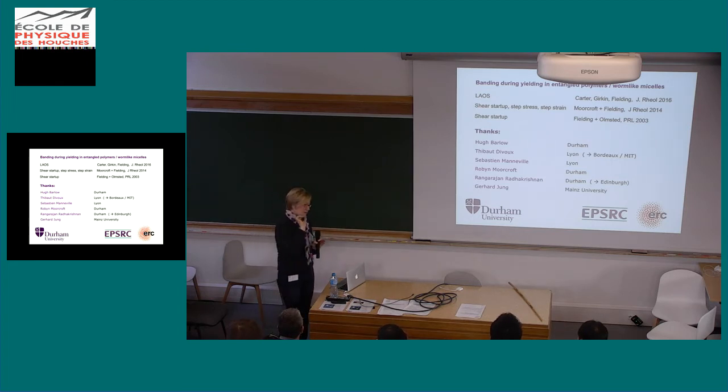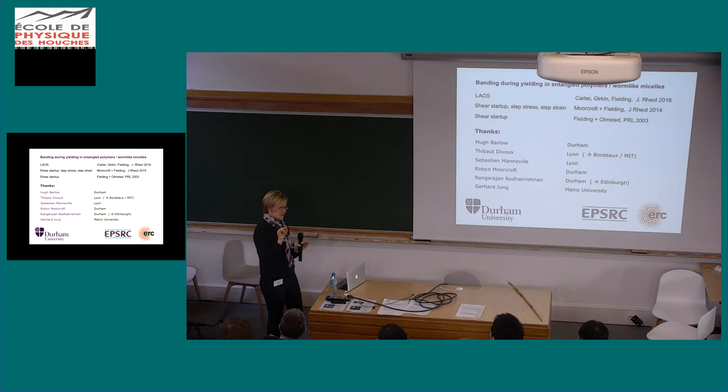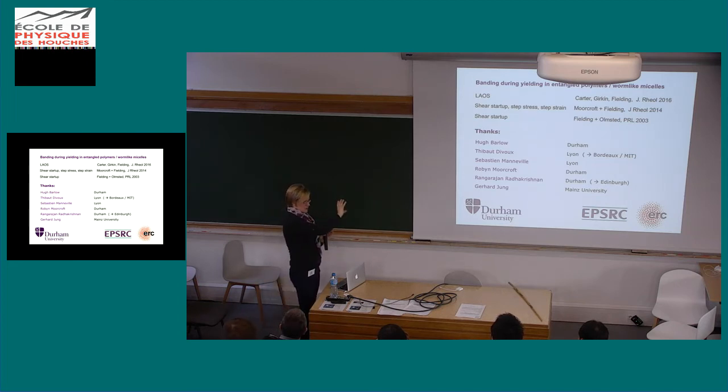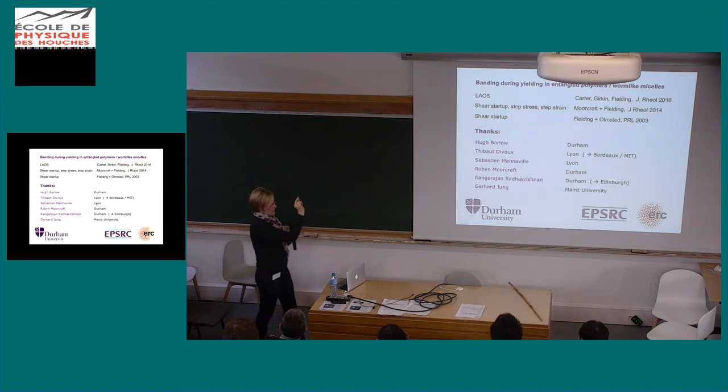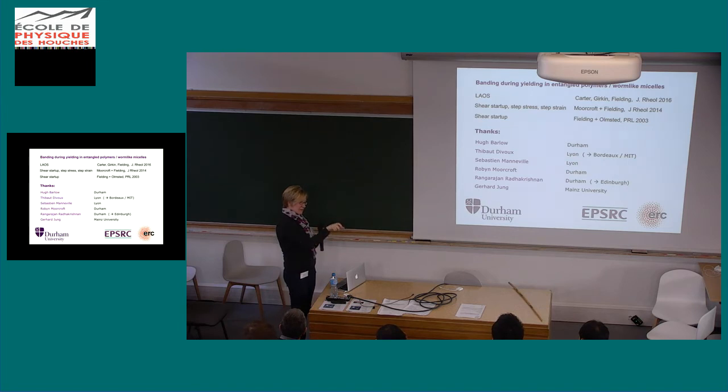And so the way that one then seeds the bands in the first place, you can either impose that there's a slightly heterogeneous stress field across, but what we actually do, well, we've explored several different ways of putting in noise to the system, but in that particular simulation there, I actually assumed a slightly heterogeneous age at the start, so it's slightly older in the middle than at the outside.